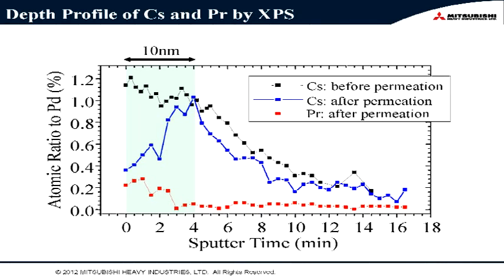And this graph shows the depth profile of cesium and praseodymium by XPS. Before permeation, this is the sputter time, and this is the atomic ratio to palladium, and this axis corresponds to the depth. Before permeation, cesium is distributed like this because we used cesium ion implantation to provide the cesium on the multilayer thin film.